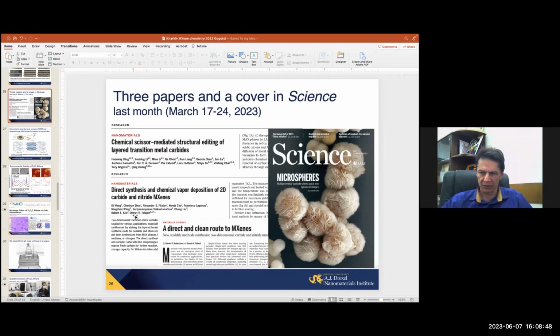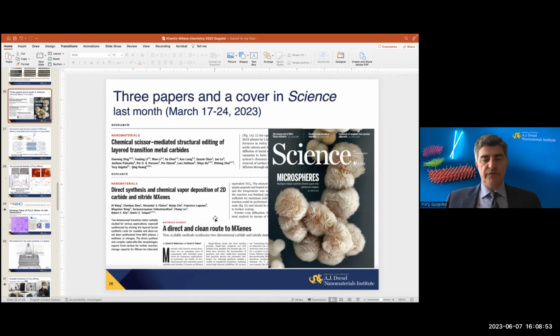I think the main advantage of growing MXene on a surface parallel to a substrate, like a silicon wafer, for example, is electronic applications. For example, monolayer titanium carbide Ti3C2, even with oxygen on the surface, has a breakdown current at the same level as graphene. So you can use it, for example, as nanometer-thin current collectors or interconnects and so on. It's also possible to make semiconducting MXene, opening a band gap by surface terminations. So I would say for electronic applications, it is certainly potentially interesting.